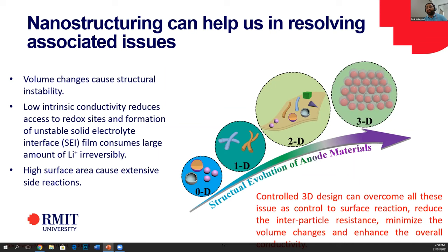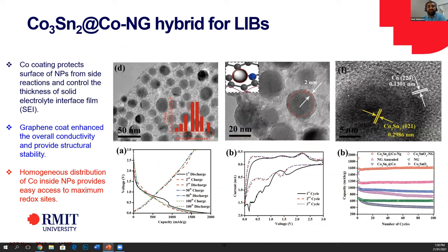So considering that, we developed a cobalt tin alloy, and tin is very active. It's an alloying based material. We put that on nitrogen doped graphene, which is highly conductive and also electrochemically active. But what normally happens with alloy based materials is that the volume change is 300%. That's a very high volume change. How can we control that? To control that, we need some surface protection. We need some cobalt coating on it.